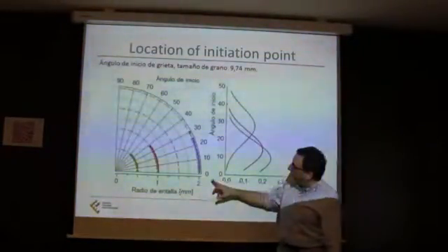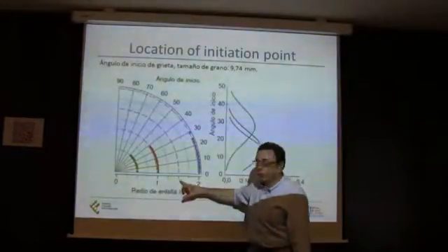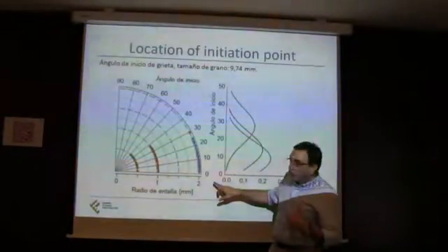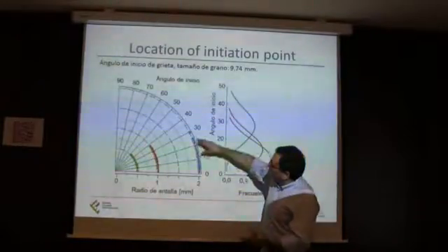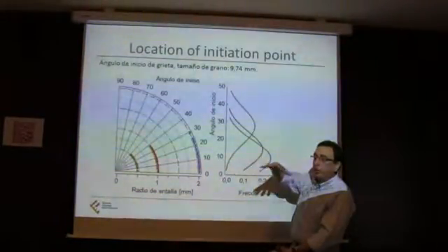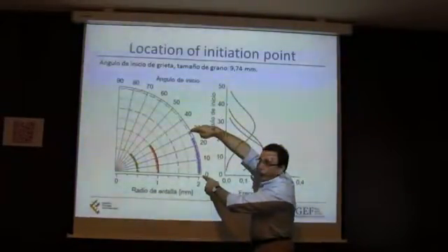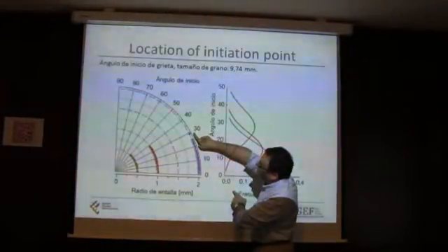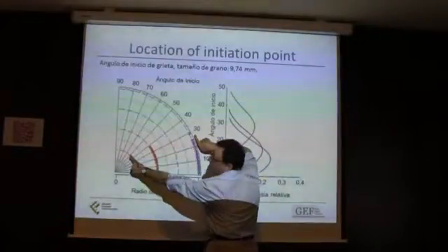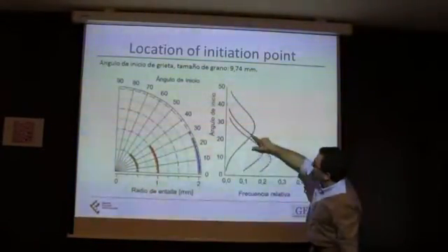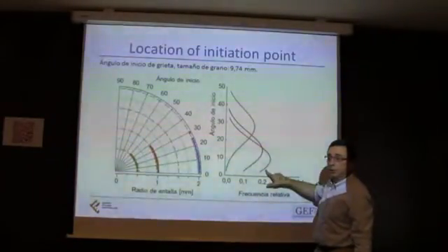This is a much better view here. This is the same microstructure, and these are the different sizes of the hole that we tried. And what we see is that as the hole gets bigger compared with the microstructure, the region where the cracks initiate diminishes. In here we are about 30 degrees, and in here we have 50 degrees, right? And you have here the different statistical distributions.